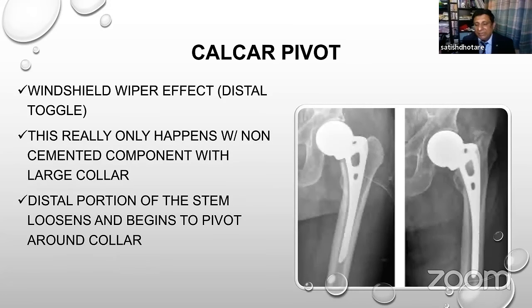Now, calcar pivot, this is not very commonly seen in cemented stems. This is more common with the uncemented stem. It's kind of a windshield wiper effect, basically. The distal stem toggles more, which leads to either fracture or breakage around the collar. Basically, because of this toggle, there will be more load on the calcar, which can break there, or it can break at the tip. That's why the collar is pivoting more on the calcar side, so there's a high risk of fractures there. This is more commonly seen in uncemented stems, and one example is the Austin Moore.